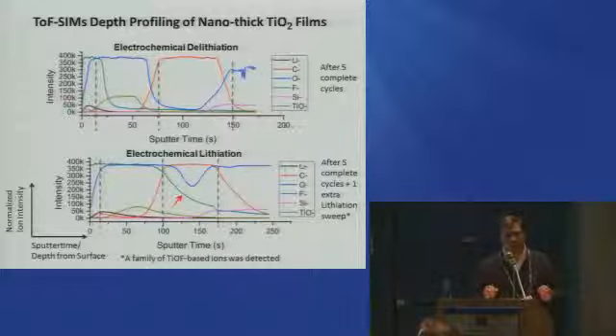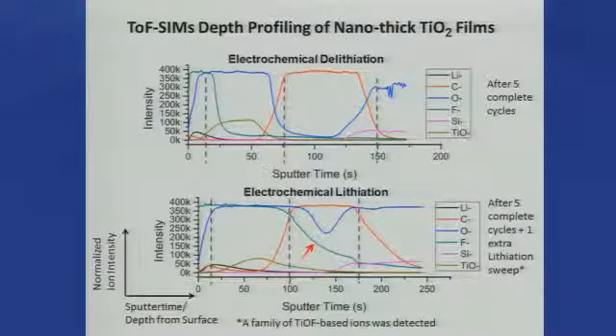However, what we can do is we can put it in the TOF SIMS and we can do depth profiling of the compositional change of lithiated TiO2 films versus delithiated films that have been cycled. And so I know this is a little bit complicated and hard to see, but this marker here for fluoride minus, for the electrochemically delithiated films, you can see that it's pretty much confined right at the interface by this dashed line. This is the surface chemistry. This is where the TiO2 film starts. This other line marks the interface between the carbon and the TiO2.